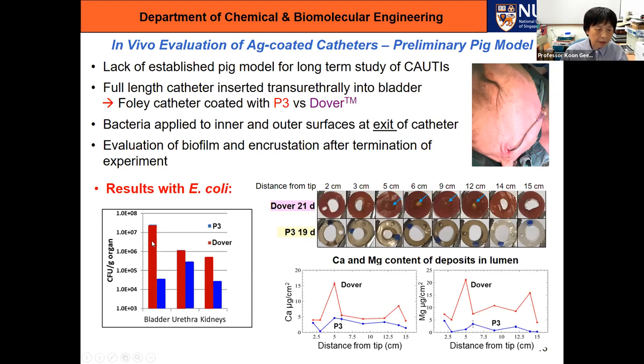This is the bacterial loading on tissues: the bladder, urethra, and kidneys. In all three types of tissues, we see a higher loading of bacteria for the Dover catheter. But what is most interesting is here. These are certain locations of the Dover catheter. We check each location, and at certain locations, we can already see blockage after 21 days. On the other hand, for the P3 catheter, the lumen is fully open. And we checked what is in these deposits. We see calcium, we see magnesium.